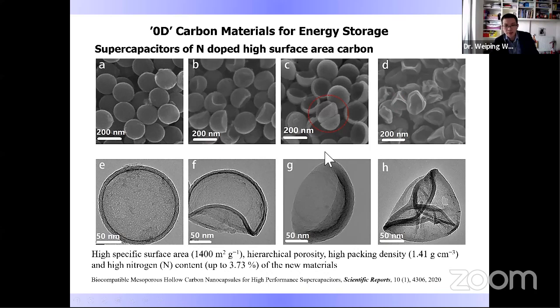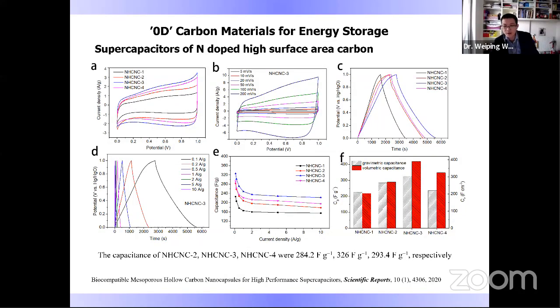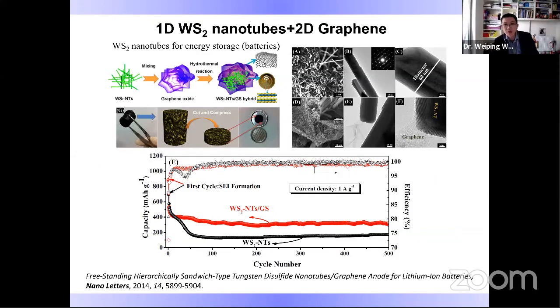Then we designed some highly ordered micro or nanostructures of carbon material with hollow structure. This high surface area carbon material can be used as electrodes for supercapacitors and has shown much enhanced performance. Also, with the philosophy of one-dimensional and two-dimensional, I have successfully demonstrated high-performance batteries with a one-dimensional tungsten disulfide nanotube and a two-dimensional layered graphene material.